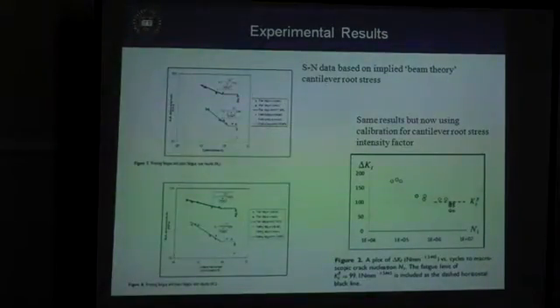Now he didn't do that. He got some notional S-N curves, which obviously n in the usual direction S appear, where the S value we used, the stress, was simply that implied by beam theory. Obviously there was nothing like that kind of thing there. It was really a notch. So simply by fitting a notch to it, you can turn that into a K-N curve, which then represents the life of the thing. I mean, you're neglecting crack propagation. You're assuming that all of the life is consumed in crack nucleation.